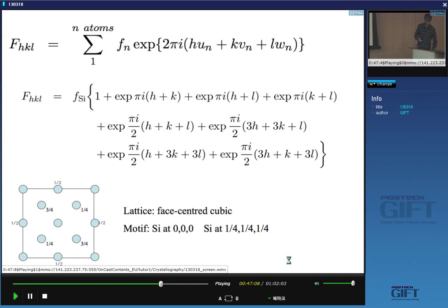Yeah. So focus again on our equation that the structure factor is basically the summation of all the scattered waves from all the scattering centers. I now have 8 atoms in the cell. Yeah, because the motif consists of 2 atoms. There's a silicon at 0, 0, 0, and a silicon at a quarter, quarter, quarter. So I have to have 8 terms for this equation here. Okay, the first term will be the 0, 0, 0 position, and then we have the face centers, and then we have the locations at a quarter, 3 quarters, quarter, and 3 quarters. So I have now 8 terms in my structure factor equation.